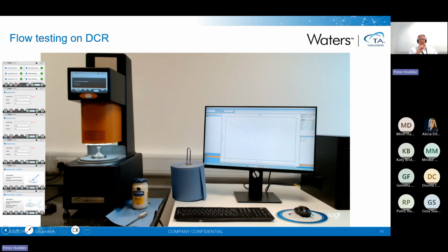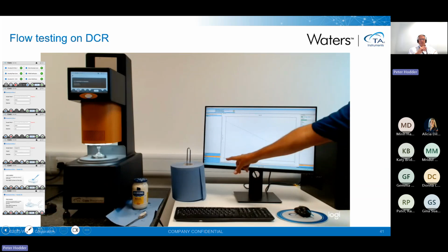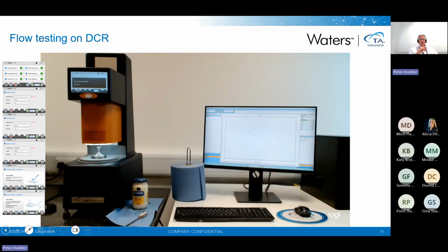Now I can choose to plot these. These are currently being plotted in centipoise. I would normally plot them in Pascal seconds because I use SI units, but because Brookfield and most viscometers tend to focus on centipoise, I've left it at that. So it's very clear that this sample is a shear thinning material. The viscosity is dropping as we go to higher shears.